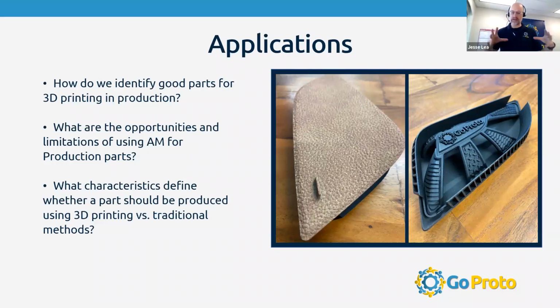If you're trying to pack a build with selective laser sintering, you add more parts, and it just means the laser has to then go trace that part. With multi-jet fusion, you add more parts, the print head is going to pass over that area anyway, and whether it drops fusing and detailing agents or not doesn't slow the build down at all. The only thing it does do is add a little bit of thermal mass, so it maybe needs to cool down, or it may affect the geometries a bit. But in terms of speed, it doesn't slow it down at all, which is fundamental. It's economics, yeah. Exactly.